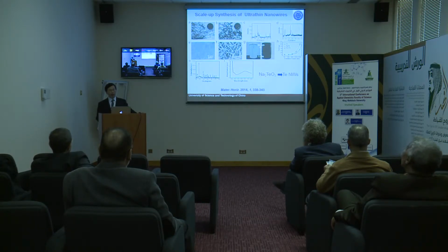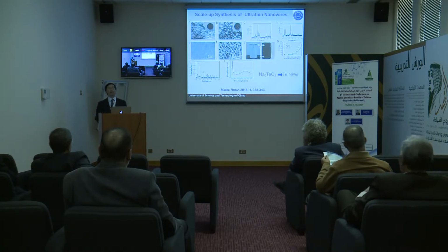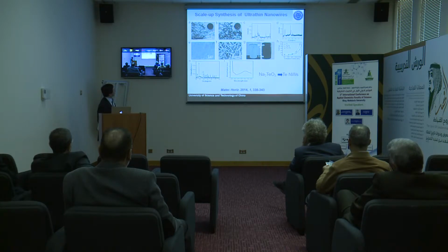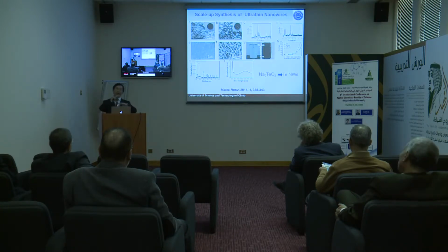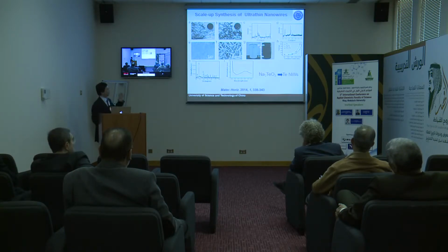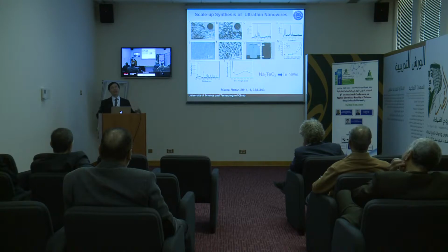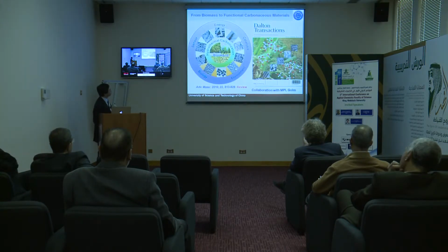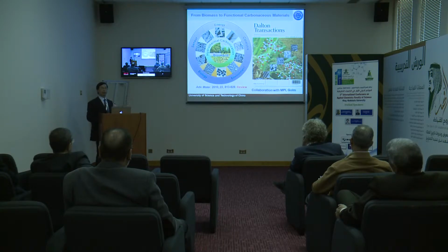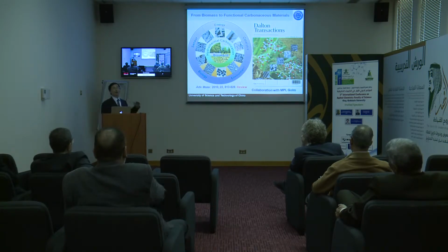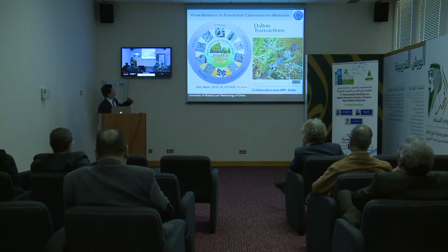Then we want to use these tellurium nanowires to get carbon nanofibers. So we do the hydrothermal carbonization on the surface of these tellurium nanowires. If you remove the tellurium nanowires, you can get this huge size hydrogel, or aerogel if you remove the water. So these are carbon nanofibers in any size, from 1 centimeter high to 20 centimeter high. So you really get a very big nanowire network. This kind of material is very useful because this is carbon. Carbon is an excellent absorbent, and even useful for doping to design new materials.